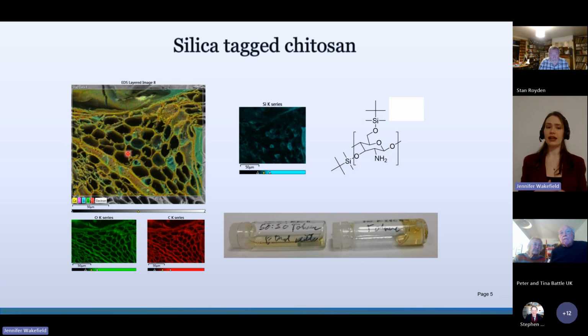So the scanning electron microscopy gives you basically a really, really zoomed in image, a microscope image where you can see down to the individual cells within the wood. So we could see exactly how the polymer was interacting with the wood. So in this case, coating the edge of the cell walls rather than completely filling the cells in most cases, which would allow the material to be retreated. Anyway, the wood is not the point of this presentation,